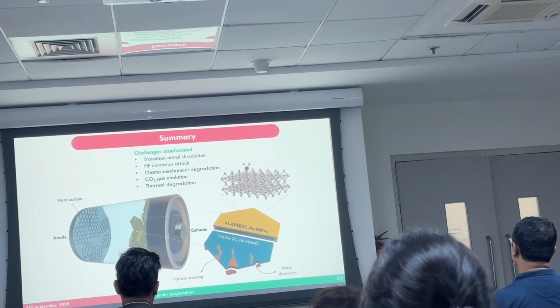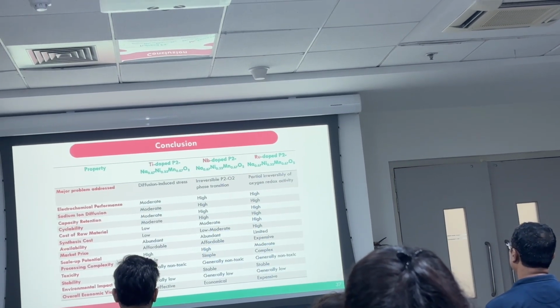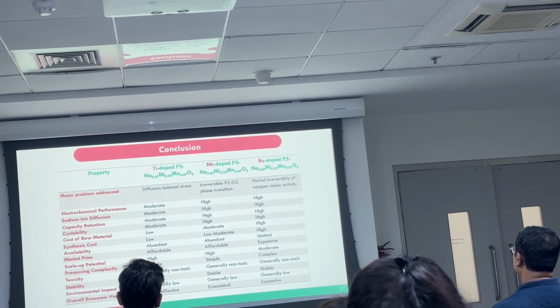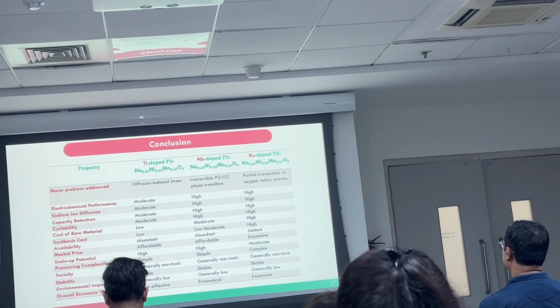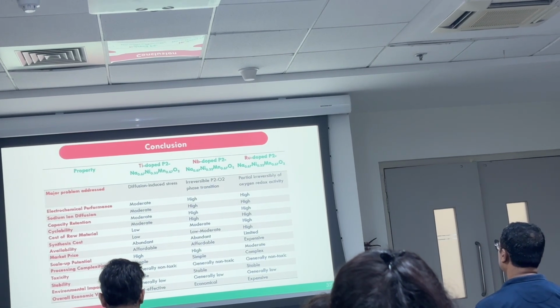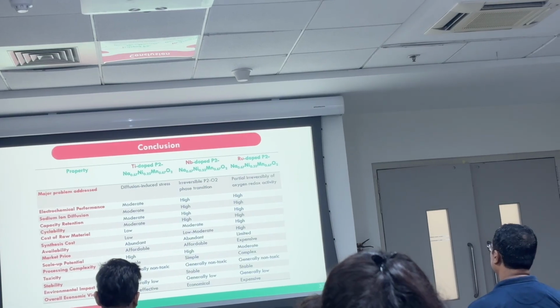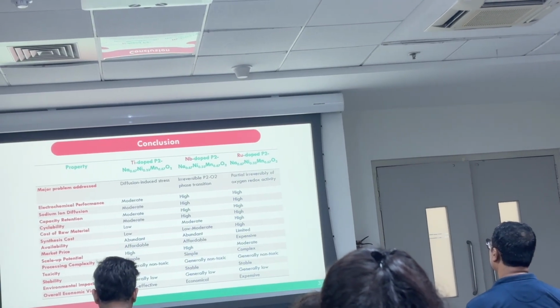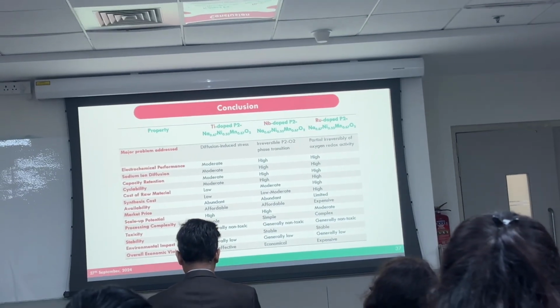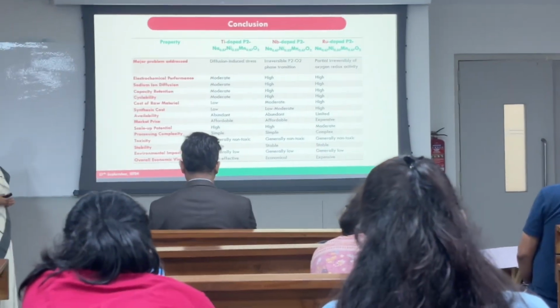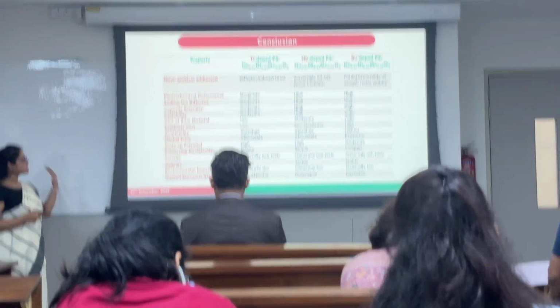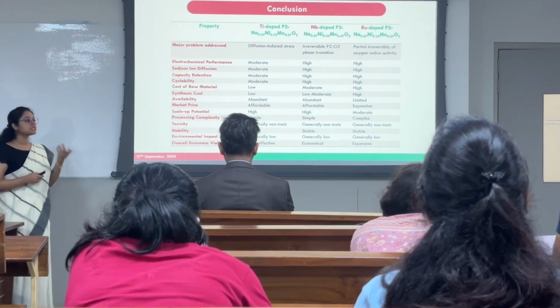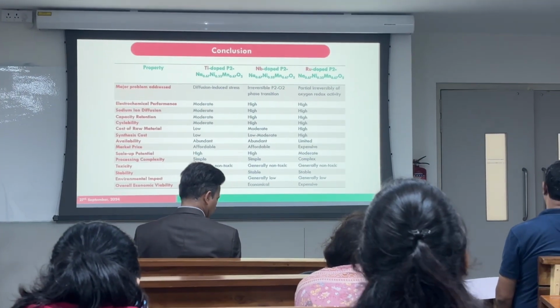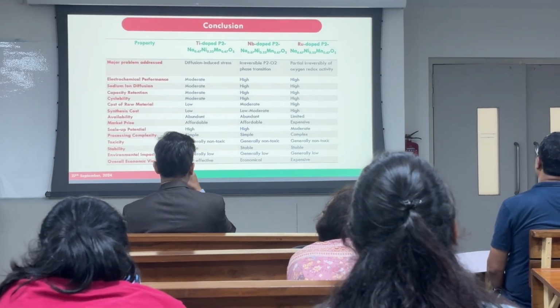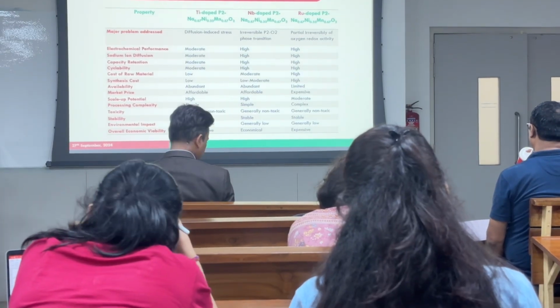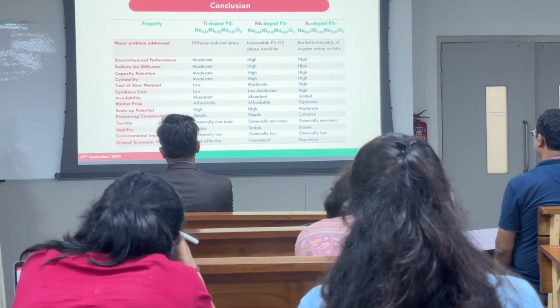In order to have a comparative study in the conclusion chapter, we considered all three cathode materials: the titanium, the niobium, as well as the ruthenium doped. And we observed that although in terms of cost, the titanium is cost effective, in terms of performance and considering all the other stability as well as the raw material analysis, the niobium doped NMNO would be economical, as well as because we could easily suppress the P2-O2 phase transition.